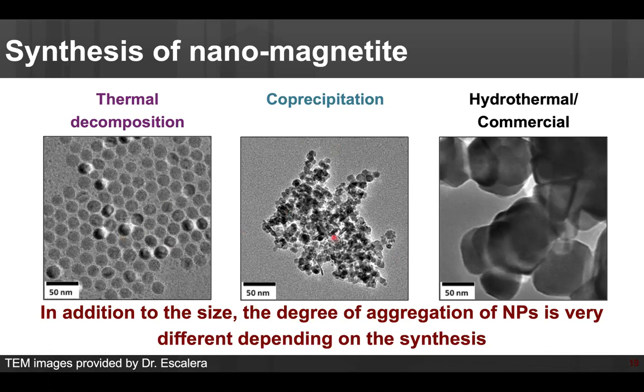Then co-precipitation, you still have really nice particles. The issue is that they tend to agglomerate in these big chunks. And then the hydrothermal, or the commercial one, this one is a material that you can go and buy. And you can see the nanoparticles are around 100 nanometers, but they are very, very agglomerated.